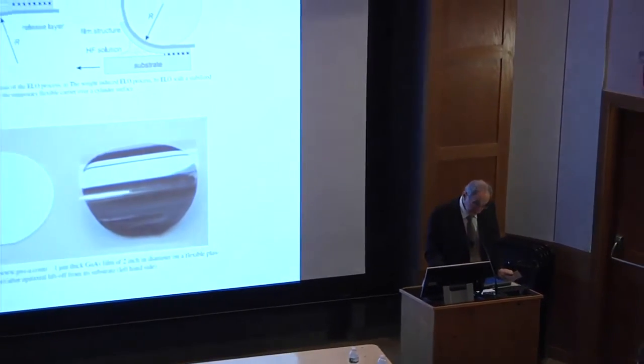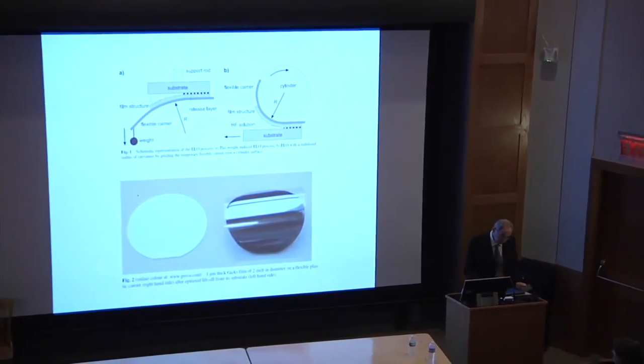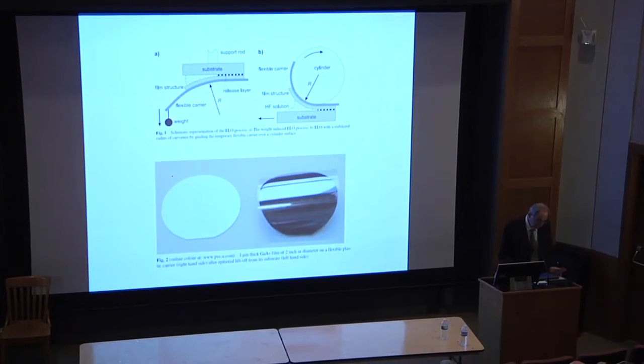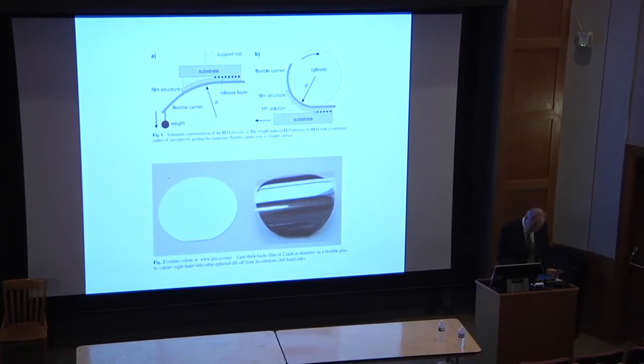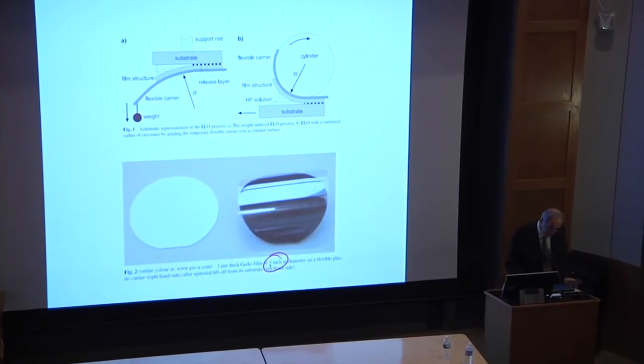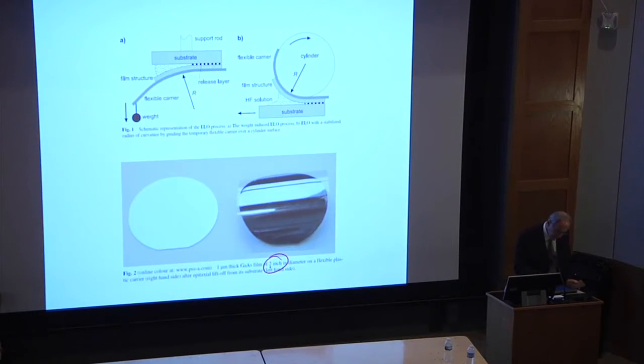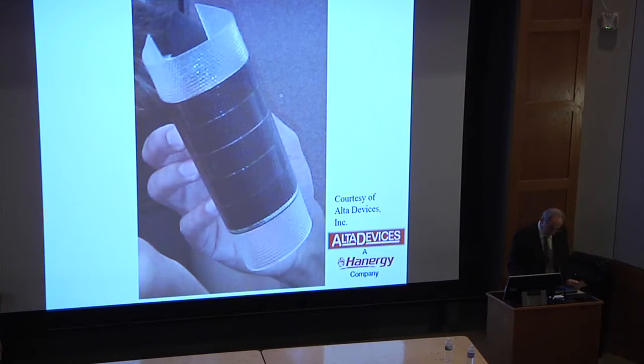It's quite amazing. This is an earlier version of this. I thought I had discovered it 30 years ago. It turns out some Japanese had actually published this about 10 years earlier, but there were various problems making it practical. This was during the era when they could only do 2 inches. But there are various ways of doing it. We don't do it this way, but they did it so they just put a single drop of acid here, and they kind of peeled it off that way. It's kind of remarkable. So this is the device. Essentially what I'm showing you here. It is actually the world's record solar cell, and so we're proud of that.